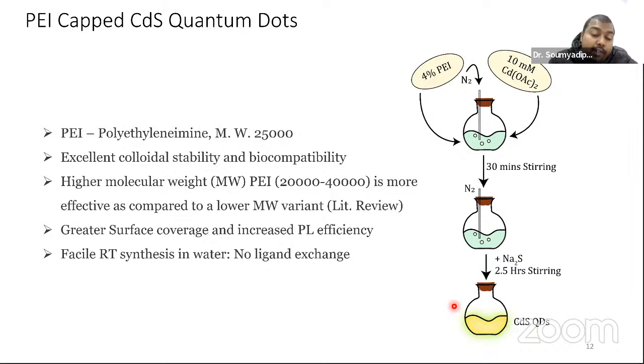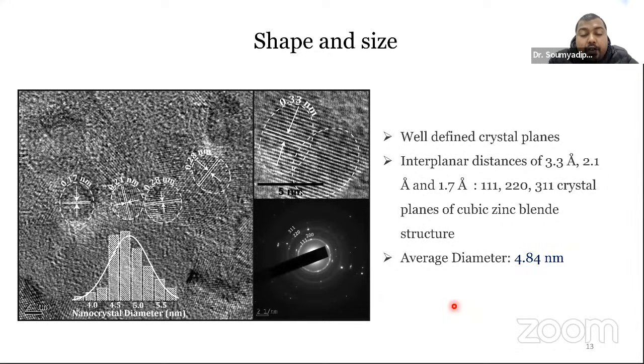Then we characterized the quantum dots via TEM. We got well-defined crystal planes, which can be ascribed to the cubic zinc blende structure of the cadmium sulfide. Now, look, cadmium sulfide is a very old quantum dot, very well studied. But after 2010 or so, the research on cadmium sulfide just stopped. I don't know why. People are much more interested in cadmium selenide, cadmium telluride, indium phosphide, indium arsenide, and other quantum dots.